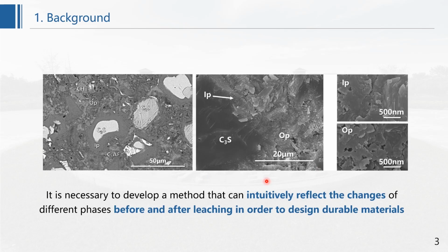As we all know, cement paste is a complicated mixture of unhydrated particles, portlandite, inner product, outer product, and aggregate. The leaching of different phases in cementitious material is a gradual process which involves dissolution and transportation. It has been a challenge to accurately obtain the change of each phase during the leaching process. So far, there is still a lack of intuitive results about the changes of different phases after leaching.